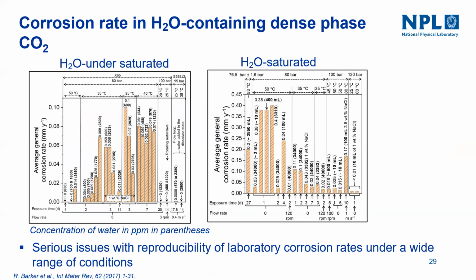So what we have done is compare the corrosion rates containing only water as an impurity, because several studies have used different concentrations of impurities. It is very complex to compare one study with another, considering that several factors influence corrosion. Even having just water as an impurity is complex, with different exposure conditions and flow rates. One thing we can see here is that H2O is undersaturated, which means H2O is in the soluble state, but the corrosion rates are significantly higher, and in some cases almost equal to the saturated limits. Once the H2O is in the soluble state, it should not condense to cause any corrosion. But we have seen reports of corrosion even in undersaturated conditions.